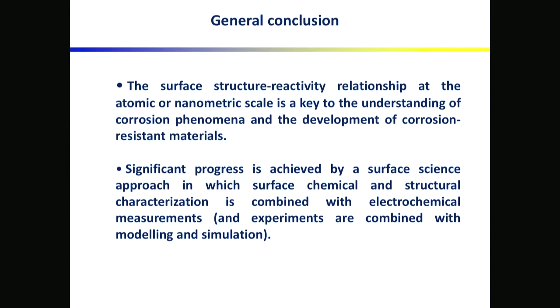So just a general conclusion here to reemphasize that the structure-reactivity relationship at the atomic or nanometric scale is really a key to the understanding of corrosion phenomena and the development of corrosion-resistant materials. And also, I hope that I've been able to convince you that we've made significant progress by using this surface science approach in which we combine surface chemical and structural characterization in situ with the STM, ex situ with the other surface spectroscopies, and combining that, of course, with electrochemical measurements, and although not shown here, combined with modeling, which we do a lot using DFT.